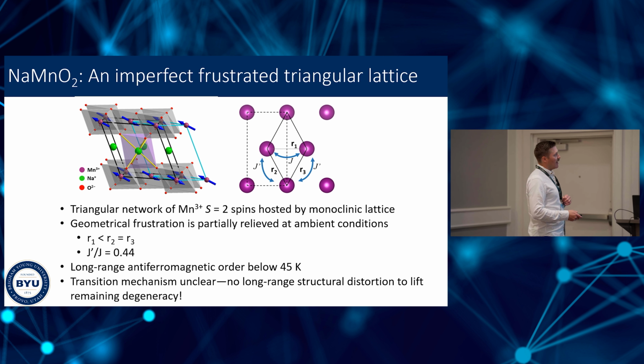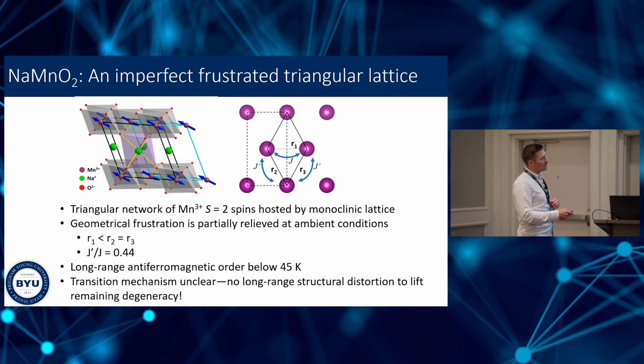And so the geometrical frustration is partly relieved because the exchange interaction between these two spins will be different than the exchange interaction between this pair and this pair. But we still have this one remaining degeneracy. R2 and R3 are equal to each other, those bonds are equivalent. So J prime, this other magnetic exchange interaction, is equivalent between these two pairs of spins.